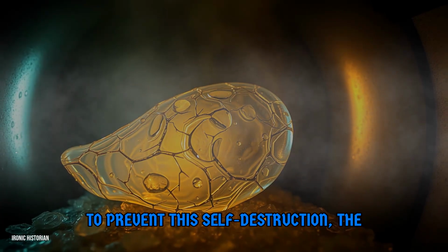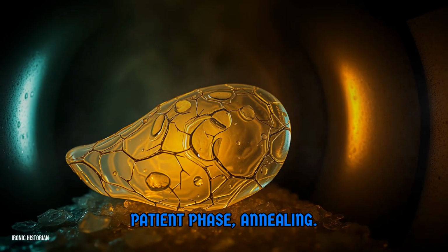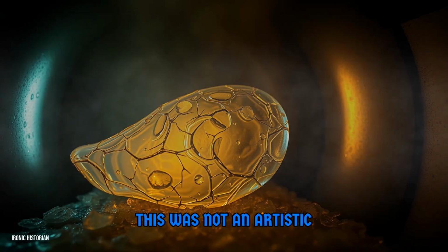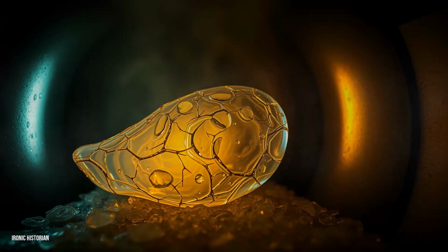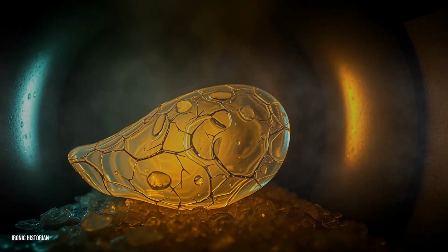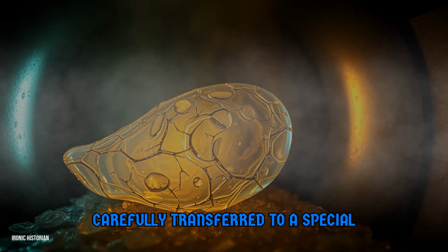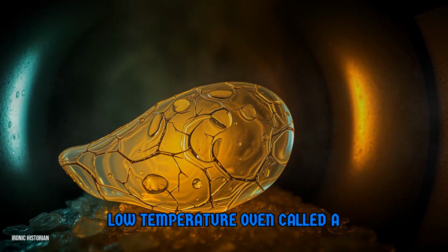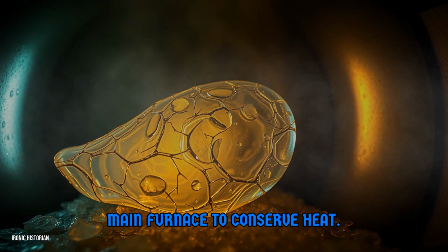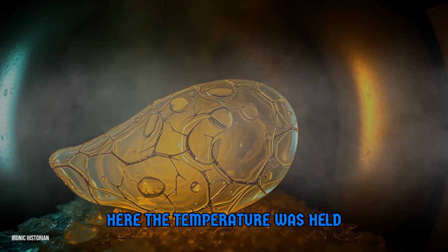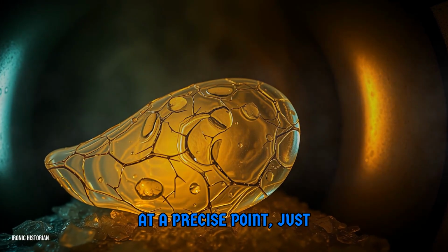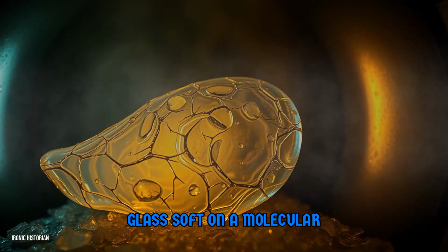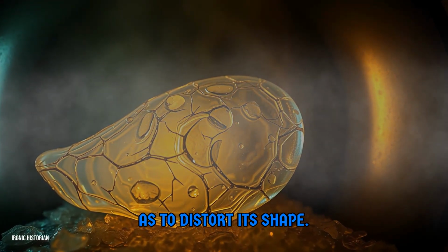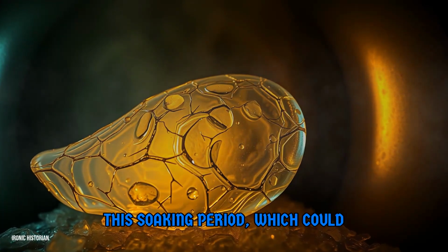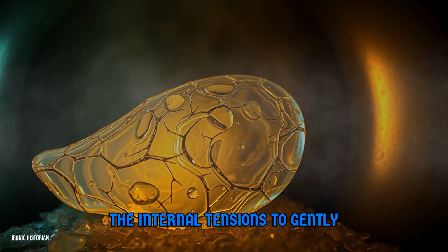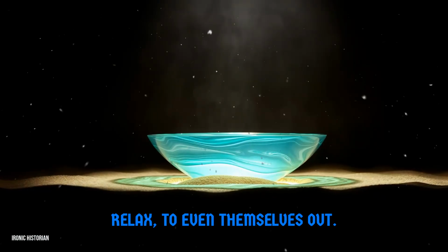To prevent this self-destruction, the glass entered its final, most patient phase, annealing. This was not an artistic step, but a scientific one, a secret recipe of time and temperature. The freshly worked piece was carefully transferred to a special low-temperature oven called a lehr, often connected to the main furnace to conserve heat. Here, the temperature was held at a precise point, just high enough to keep the glass soft on a molecular level, but not so hot as to distort its shape. This soaking period, which could last for many hours, allowed the internal tensions to gently relax, to even themselves out.